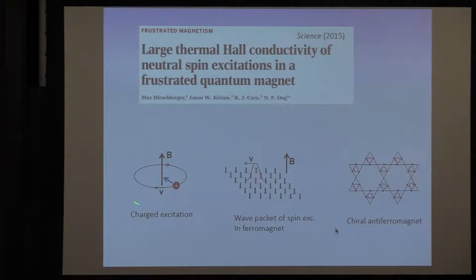So for a Lorentz force with a charged particle, this is the familiar cyclotron motion that leads to the Hall effect. So the question is, if you had a wave packet of spin excitations, can a magnetic field bend its path to give you a Hall effect? And the original Nagaosa-Lee model was based on this chirality of the Kagome lattice.